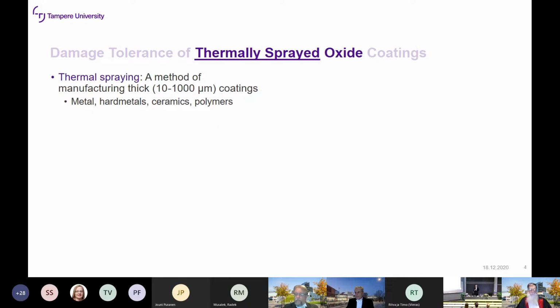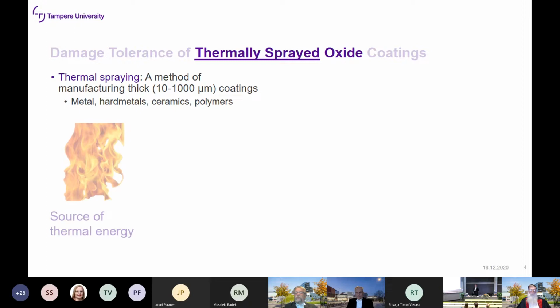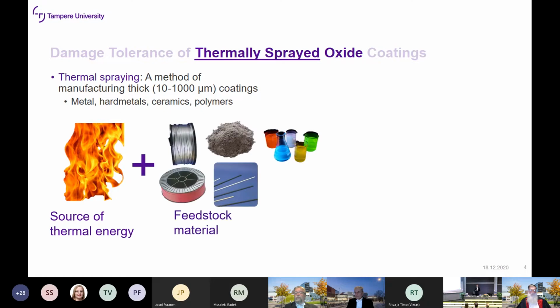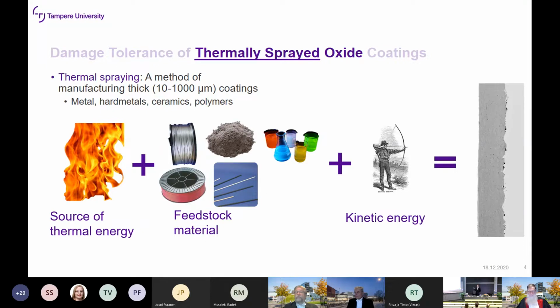What is thermal spraying then? Thermal spraying is a method of manufacturing thick coatings, so between 10 and 1000 micrometers. They can be virtually from any material group, so metals, hard metals, ceramics, or polymers. And to make those, we need heat to melt a material that can be in the form of powder, wire, cord, rod, or more recently liquid suspensions or solutions. And once we have this molten material, we need to propel it towards a surface which we want to coat. And after this, the molten material hits the surface and makes a coating such as this one. The gray part here would be the coating, ceramic in this case, and a metal substrate.